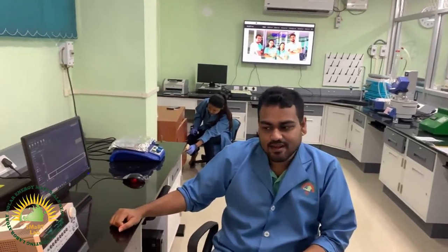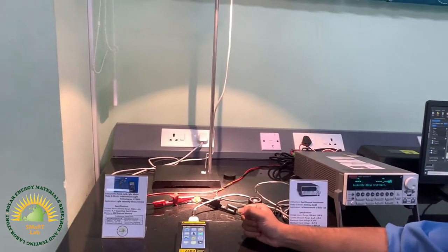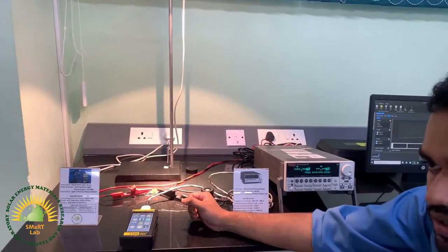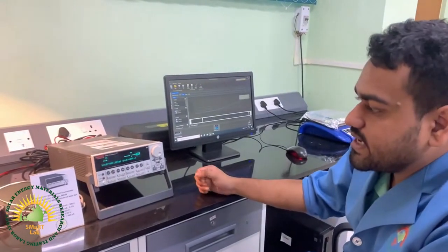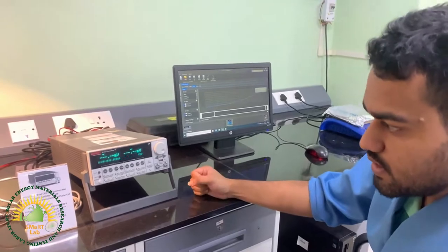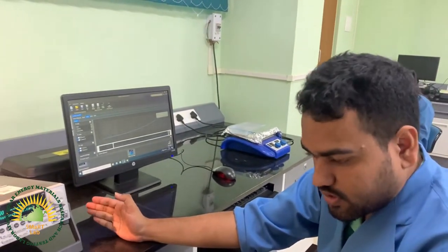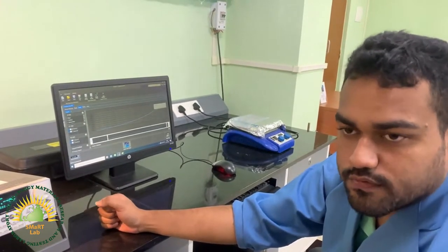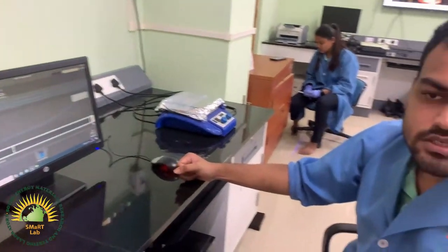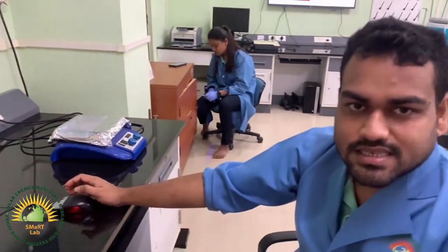So I am ready with the explanation for the photovoltaic part. We are testing the IV characteristics of a dye-sensitized solar cell prepared in our lab. First we measure the light intensity, which is 1000 W/m² — a one-sun condition. Then we test the IV characteristics using a source meter provided by Keithley. We perform a voltage sweep to get the short-circuit current range, and then using a current bias we get the VOC of the cell. Finally a voltage sweep gives us the full IV curve of the prepared cell.